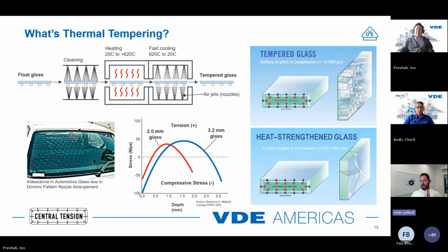You can look at it as how quickly you cool down your glass and what your thermal preheating is. You can affect that thermal tempering of the glass. And again, as you get thicker glasses and get to what they consider fully tempered glass, that's just a function of being over 10,000 psi. But I want you to keep in mind that these aren't binary applications.